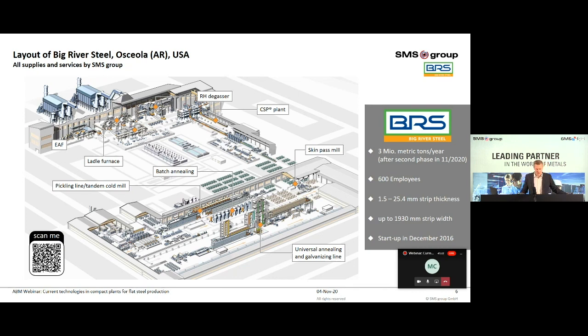The illustration shows the whole plant after the second phase with the ability to produce 3 million metric tons per year. The second phase is under execution and will be started up next week. The steel melting plant consists of 2 electric arc furnaces, 2 twin ladle furnaces, and an RH degasser. The hot strip production is done by 2 CSP strands with a 6-stand finishing mill. For cold processing, a pickling line, tandem cold mill, batch annealing furnaces with offline skin pass mill, and a universal annealing and galvanizing line are installed.